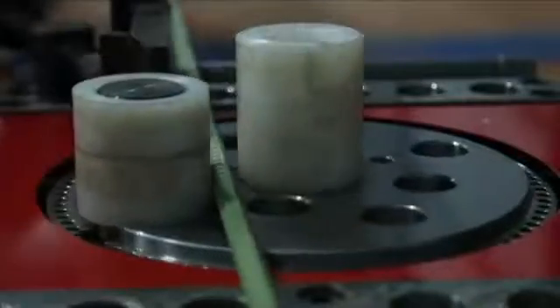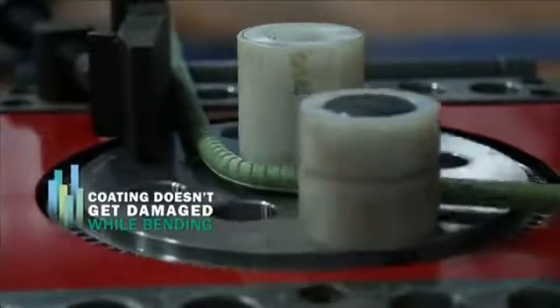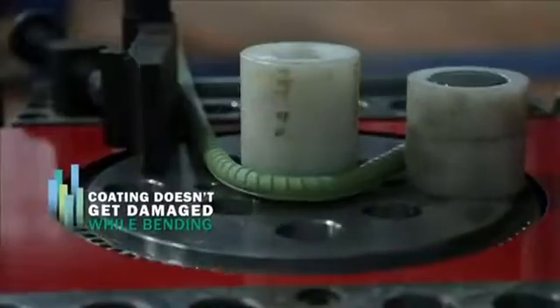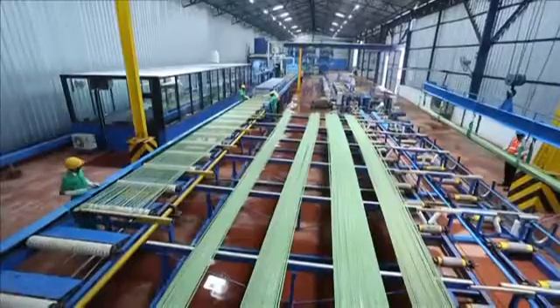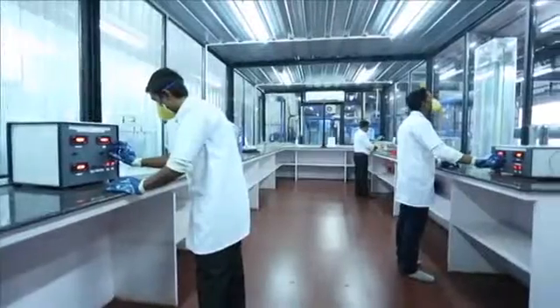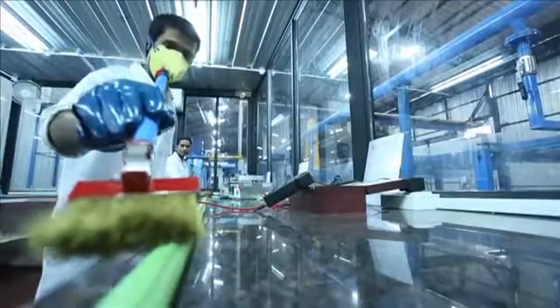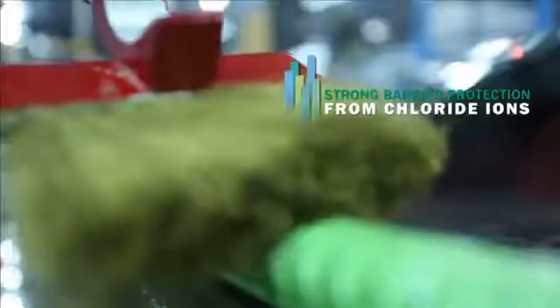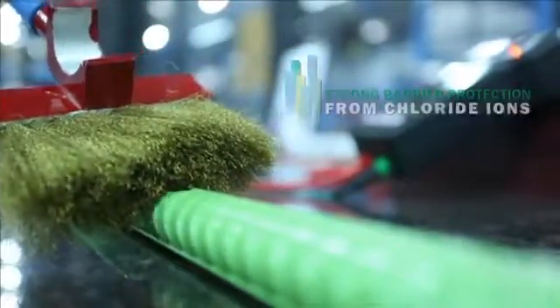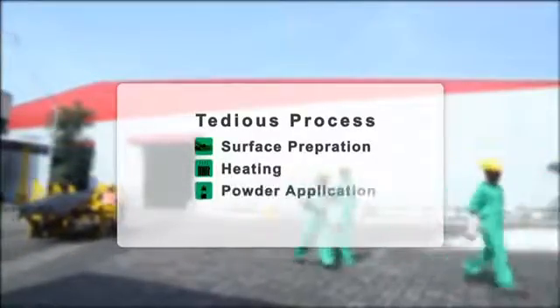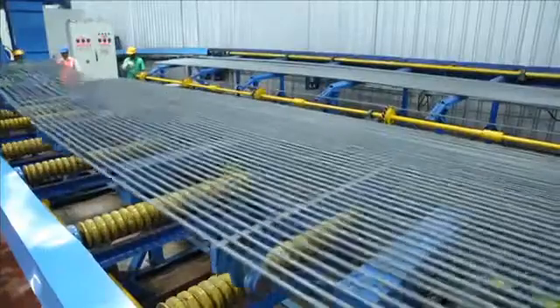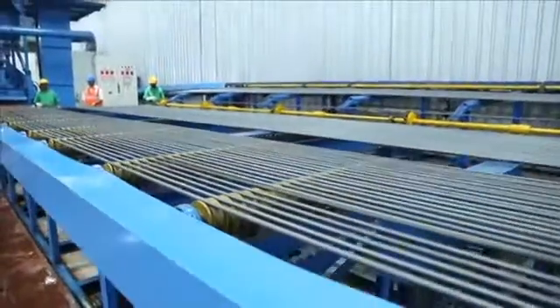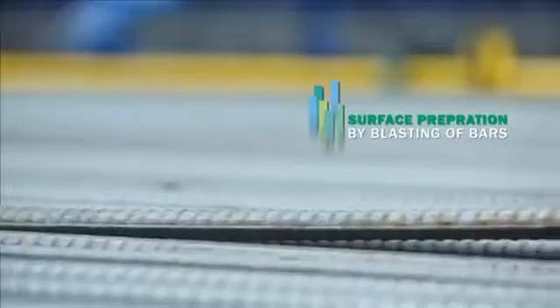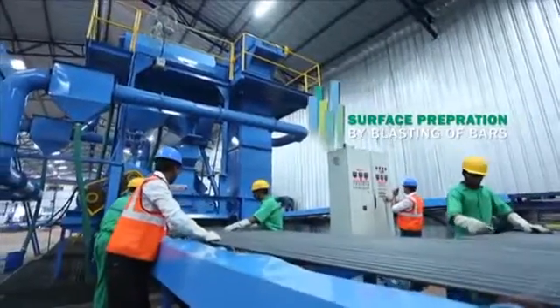Because of flexibility, the coating does not get damaged when the straight bar is bent during fabrication on a special mandrel. FBE acts as an insulator for electrochemical cells and offers a strong barrier protection to steel, which prevents chloride ions from passing through it. There are four long, tedious processes in the coating: surface preparation, heating, powder application, and cooling. Surface preparation is by blasting of bars. Impurities are removed from the surface through surface preparation.